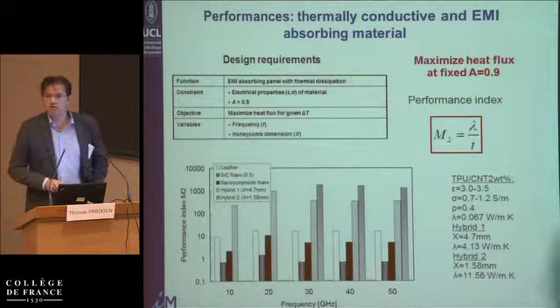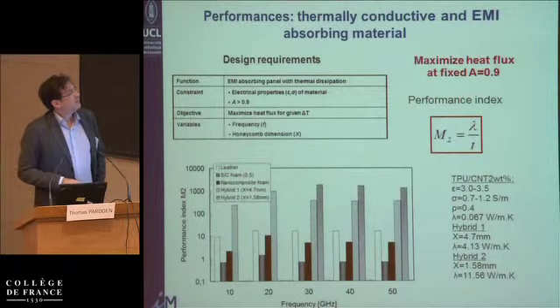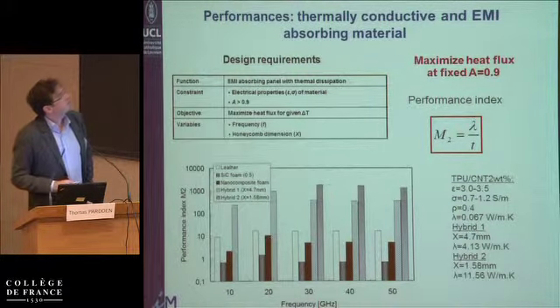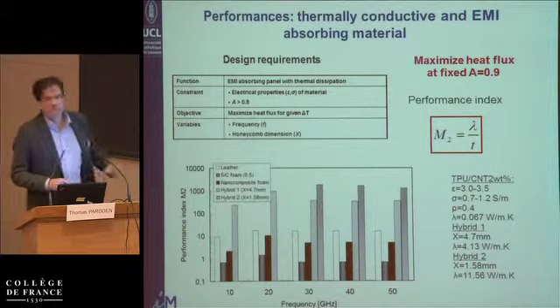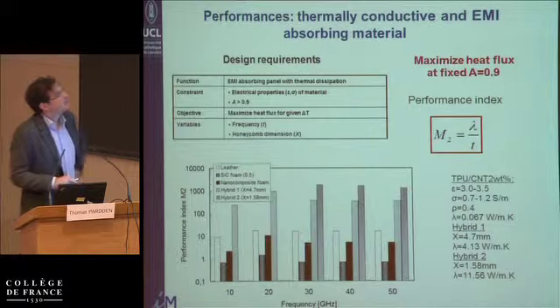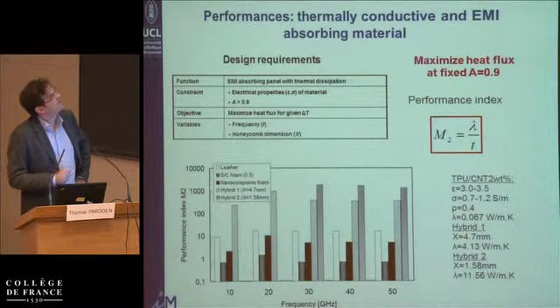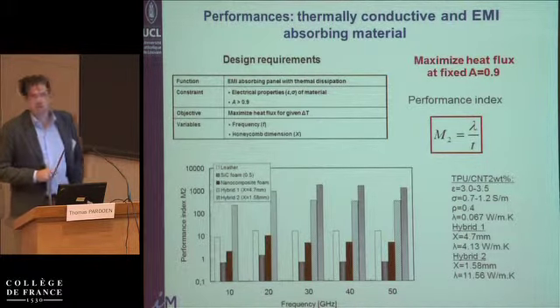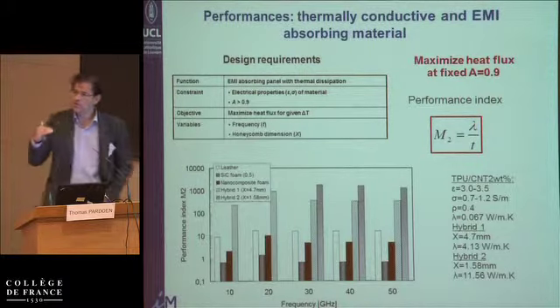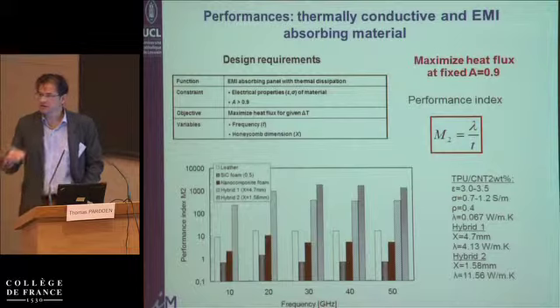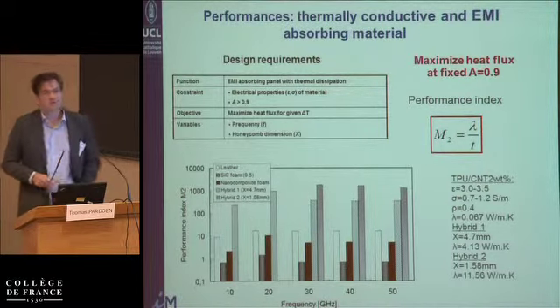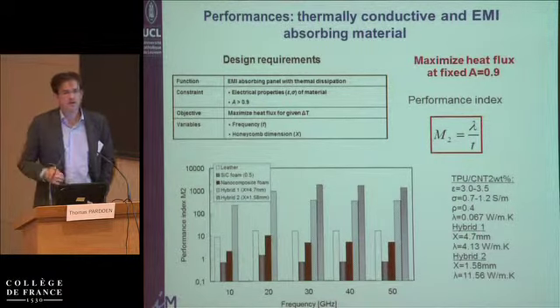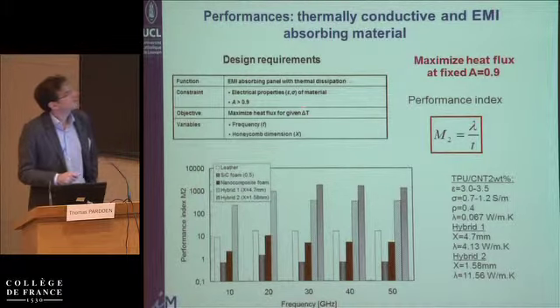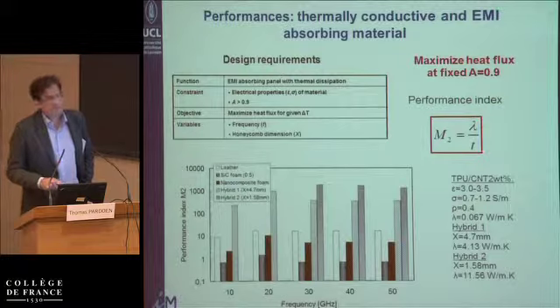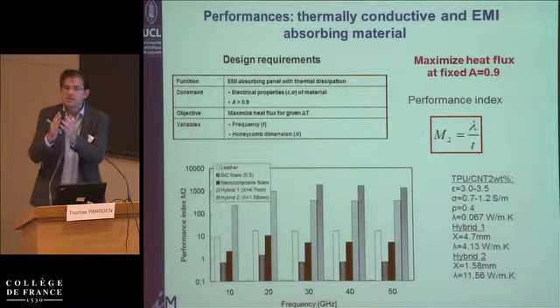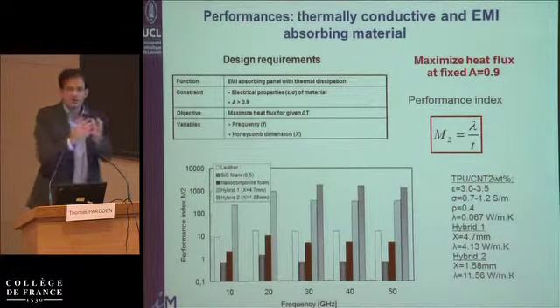So we really played the game of looking at some optimization, for different kinds of constraints, different objectives, different variables. This is just one example to show you that you can push the strategy using the approach of Ashby until the end. If you look at a material which absorbs electromagnetic power and has optimal thermal dissipation, you can set a value of absorption, 90%, 95%, as a constraint, and then, for instance, maximize or minimize heat flux. Maximize would be for a thermally conductive material, which is not the best for our material. The performance index then becomes the thermal conductivity divided by the thickness, and the thickness is hiding the absorption capacity.